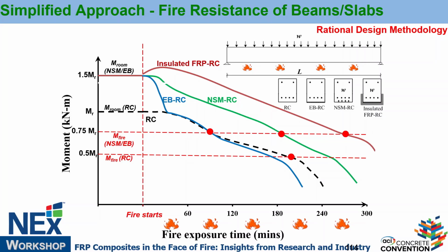Nothing happens for 60 minutes, then it starts to lose. Remember, it has to carry lower service loads, right? So because of that, your concrete beam fails here, because the load level is approximately 50% of the capacity, the service load. So it fails right here. But if you strengthen with EB, you increase the capacity 1.5 times. Then when there is a fire, it starts to decrease. Because your glass transition temperature is reached, it starts to behave just like a concrete beam, but it fails here because it's carrying a higher service load.